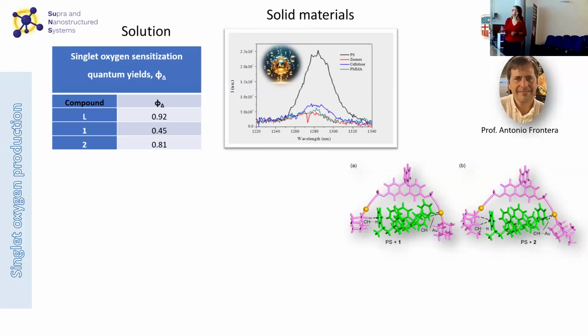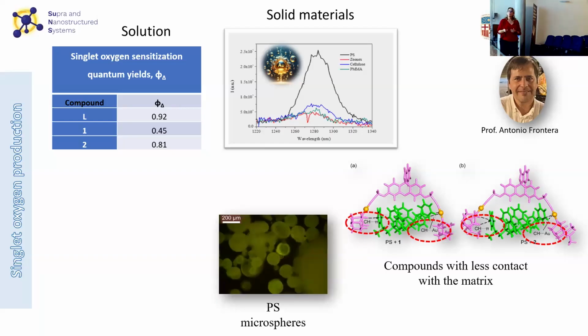And again, in collaboration with Tony Frontera, he made some calculations, and we could know that, in fact, in the case of the polystyrene, this molecule presents weak interactions, but it is the case where the fluorophore, the chromophore, is less in contact with the matrix, and for this, it seems that it can be more easily in contact with the oxygen, making this singlet oxygen generation. So if this was right, maybe if instead of having these thin films, we can improve even the surface of contact with the oxygen, the singlet oxygen generation could be even enhanced.